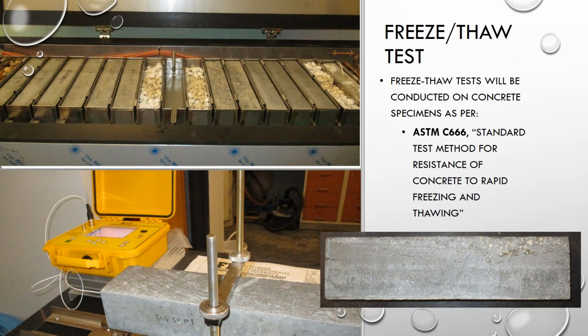And so we also conducted other tests that we want to correlate with the water pressure test. We conducted the freeze-thaw test. And so we had the same samples cast at the same time, made into prisms, and we ran the ASTM C666. You see a picture of it inside the chamber during testing or after testing, and also looking at the longitudinal resonant frequency of the sample afterwards. This is an example of the concrete prism after freeze-thaw testing. You can see the damage due to frost.